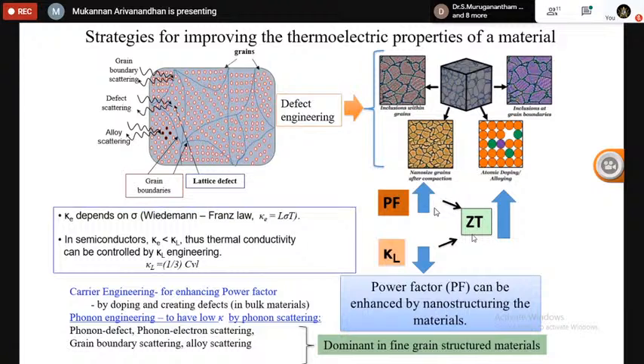People are working on nanostructured material by creating a lot of defects like these, such as inclusions at the grain as well as at the grain boundaries, as well as alloying and doping. All these things are quite useful for creating phonon scattering centers, and that will effectively control the lattice part of thermal conductivity and lead to an enhanced figure of merit. Okay, so in that aspect, we are also working on carrier engineering for enhancing the power factor, as well as grain structure engineering, one can control the lattice part of thermal conductivity, and in that way we can enhance the thermoelectric performance.